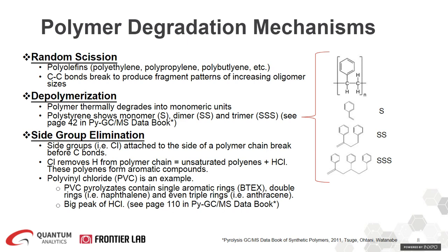Usually polymers can go through three main degradation mechanisms. Of course, depending on the mixture, the polymer might go through one or a combination of random scission, depolymerization, or a side group elimination. So for random scission, polyolefins such as polyethylene, polypropylene, and polybutylene are very good examples. In this case, the C-C bonds break to produce fragment patterns of increasing oligomer sizes. In a depolymerization mechanism, polystyrene can be a good example, and in this case, the polymer thermally degrades into its monomeric fragmentation. So for polystyrene, you'll see a styrene monomer, dimer, and a trimer.